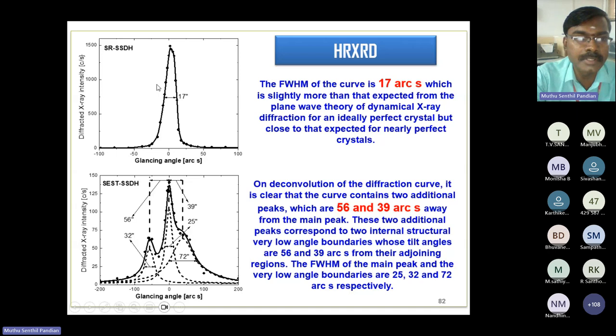This is one more example. This is for the SR method grown SSDH, sodium sulfate dihydrate single crystal for nonlinear optical application. The FWHM, full width at half maximum, of that pink colored SSDH single crystal is 17 arc seconds, which clearly indicates that the crystalline perfection of this SR grown crystal is superior to the conventional method grown SSDH single crystal.